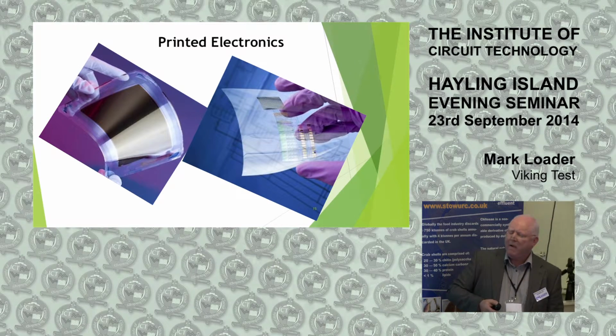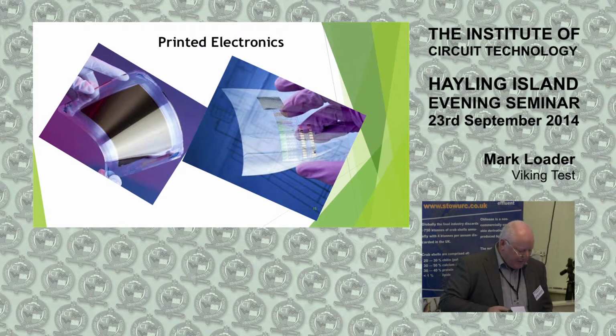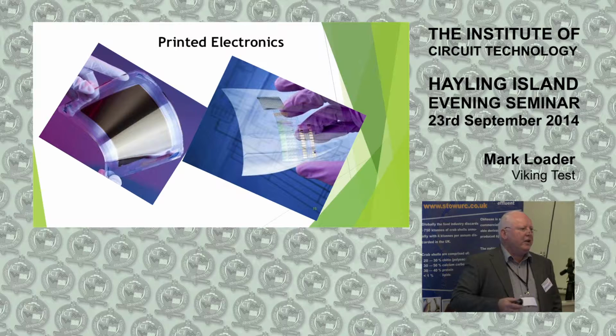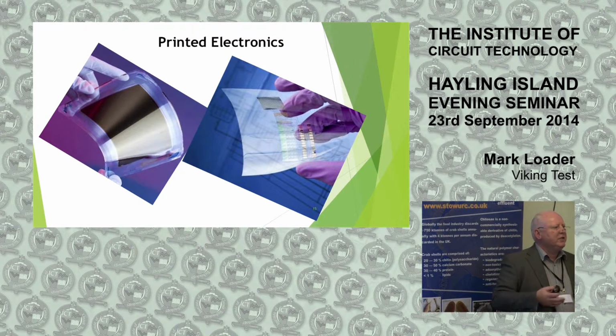Sintered varieties, such as copper and carbon, usually put down a much thicker deposit on the substrate. They use an IR head to sinter the material, or meld the material. And they commonly run at temperatures around 140 to 220 degrees C. Most people using PET materials understand that temperature can be quite difficult. It's the speed at which the head passes over the top of the material that allows it to sinter the copper without damaging the substrate underneath.